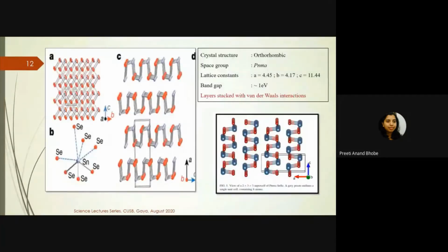And that is how the crystal structure of it looks. The low thermal conductivity of this material comes from its layered kind of structure. If you see this structure, it's a zigzag kind of structure. And each of these zigzag planes is held by van der Waals interactions. One zigzag line of atoms is there, but that line is over another line, but there is no strong bonding between the two lines, two layers. There is a van der Waals attraction between the layers.